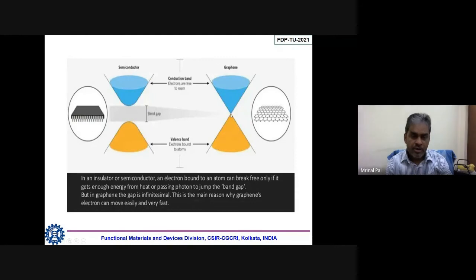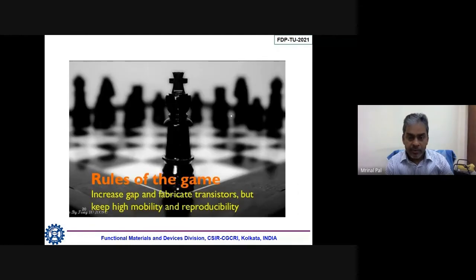The most important part is, if you can bring a certain gap in graphene, meaning you have to separate it a little bit, then only will you be able to use it in electronics. So the rule of the game is you have to increase the gap a little bit, keeping all the other parameters almost fixed, like mobility, like transparency, everything. So that is the rule of the game. As graphene is conducting, as graphene has the valence band and conduction band in contact at the K point, it will be like a conductor. So it cannot be used in electronics. So you have to create some gap.